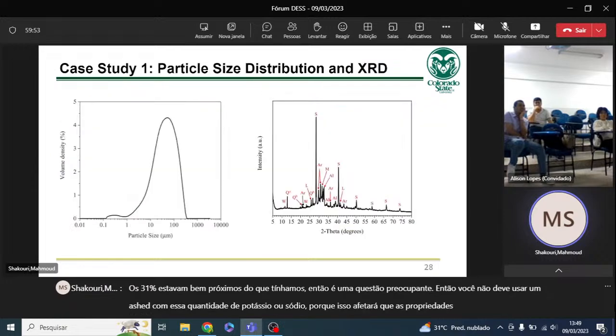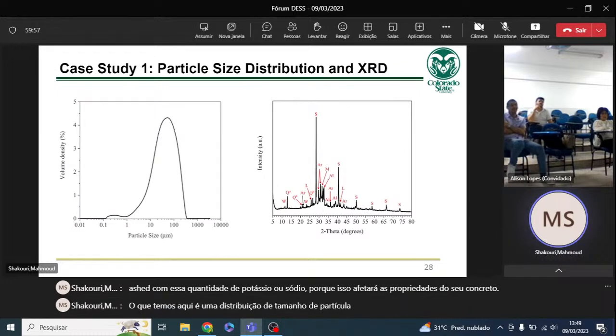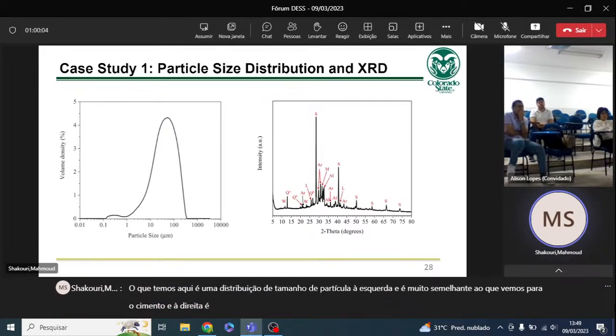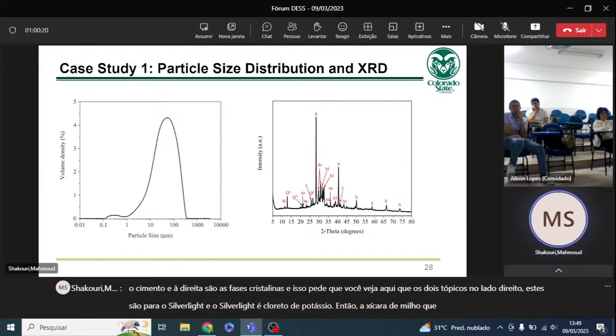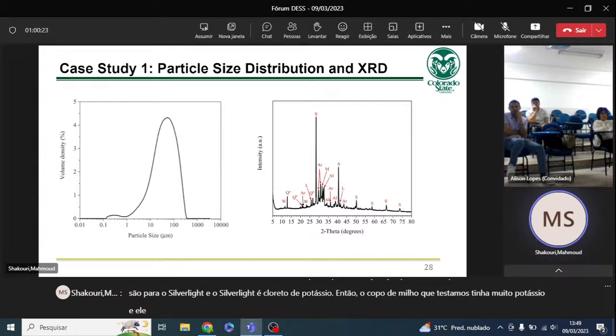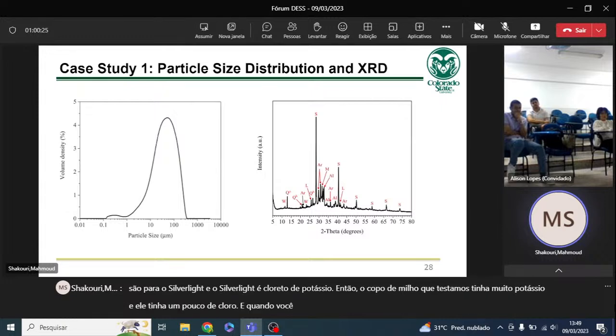of your concrete. What we have here is a particle size distribution on the left, and it's very similar to what we see for the cement. And on the right is the crystalline phases. And this S that you see here, the two tall peaks on the right side, these are for sylvite, and sylvite is potassium chloride. So the corn cob that we tested had a lot of potassium and it had some chlorine. And when you burn that, you're producing that sylvite.